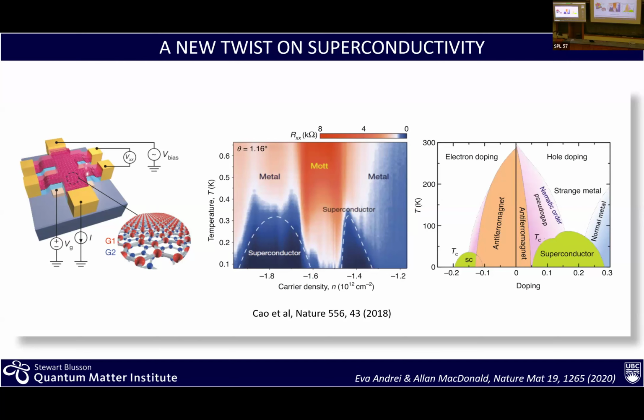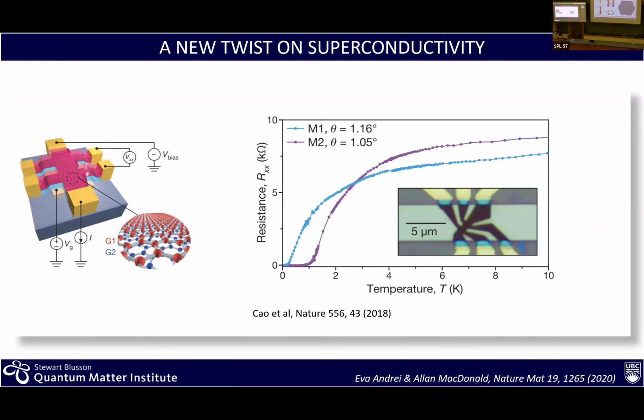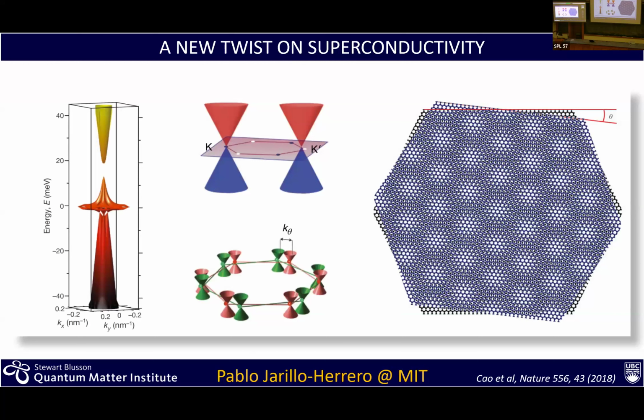So the two systems in a way are very different. In the twisted cuprate, the key effect is not associated with the moire superstructure. It has to do really with the alignment of these superconducting gaps. In this case, the details are really dependent on the moire superstructure itself. So the band engineering that we see here, this is actually a movie that Pablo always shows, where you can see as you change the angle, there's a lot of action right here. So that's extremely dependent on that.